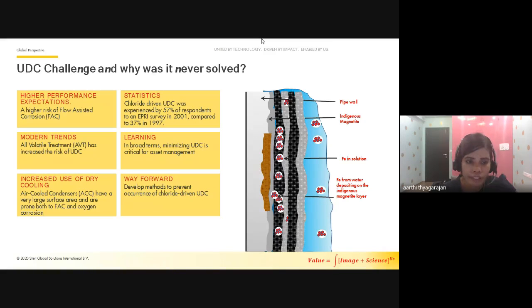Now, the second point of AVT, all volatile treatment. What happens here is industry guidelines have generally moved away from the more benign phosphate treatments, and now there is a strong steer towards the application of all volatile treatment for systems that have very clean makeup water and are able to strictly control the buildup of impurities in the steam generators. In doing so, this has resulted in a decrease in the ability of the system to buffer the pH and to deal with any contamination that does occur. And so this also unfortunately leads to the risk of UDC.